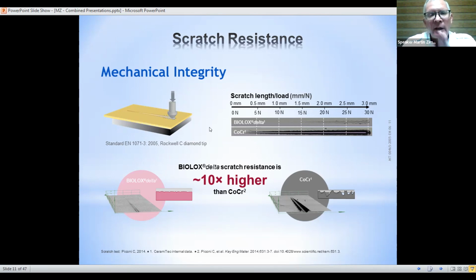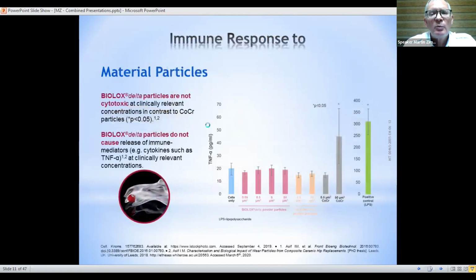The question arises now: okay, we have much less particles with ceramic, but what is the impact of the ceramic particles in the body? This has been studied at Leeds University, looking at the impact of different material particles on the cytotoxic reaction of the body. And we can see, at what we call clinically relevant concentration, for all ceramic kinds, the Biolox Delta and the Biolox Forte, there are no reactions in the body that cause release of immune mediators like cytokines at the relevant concentration, which is not the case, as you can see, with cobalt chrome. So not only is it important what type of material particles you have, but also the concentration. And that's exactly the problem with the cobalt chrome.